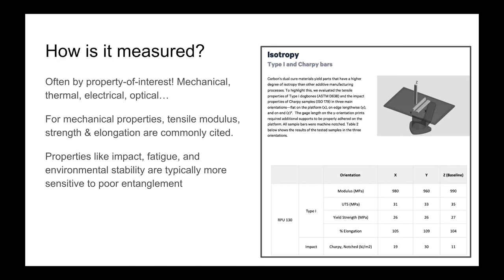For example, RPU 130 is a tough rigid material that is virtually isotropic when tested to ASTM tensile standards, but does show orientation differences in impact values. This is included here to help designers and engineers make the right choices. You can be sure if the part shows anisotropy in tensile properties that these are only magnified in more stringent testing.